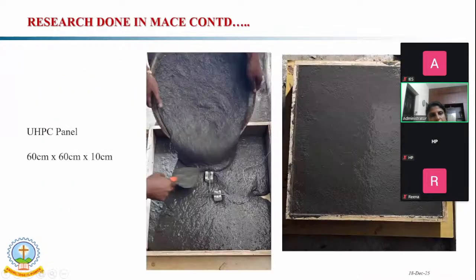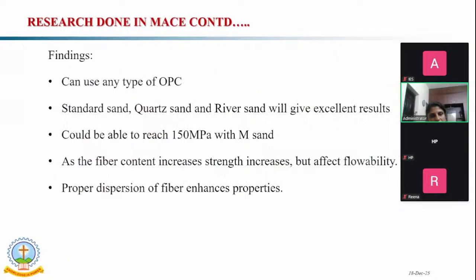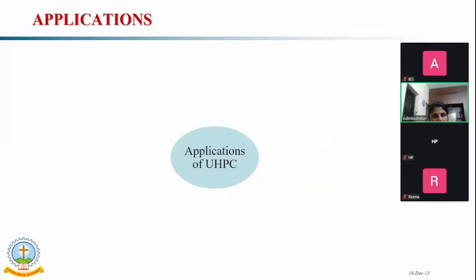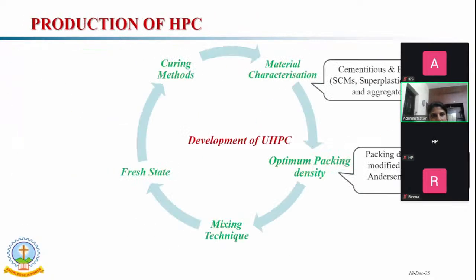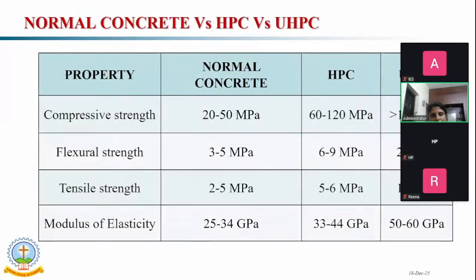Then, to achieve high performance concrete without fiber, we got results up to 110 MPa. When we compare the strength parameters, I have shown one table comparing normal concrete, high performance concrete, and ultra high performance concrete. When we compare normal concrete and UHPC, the strength parameters are much higher, including the modulus of elasticity.